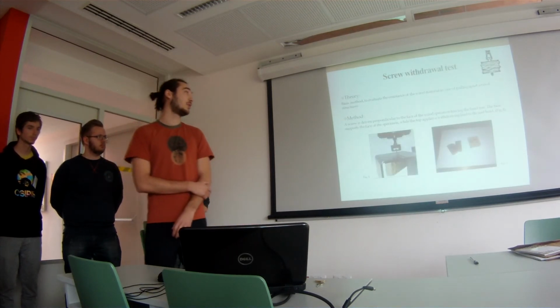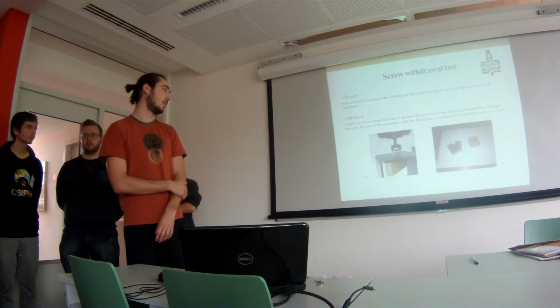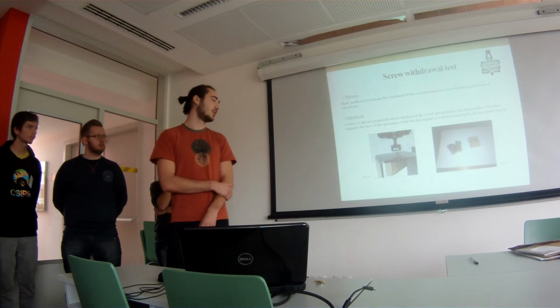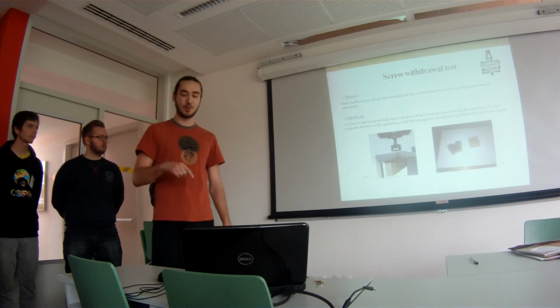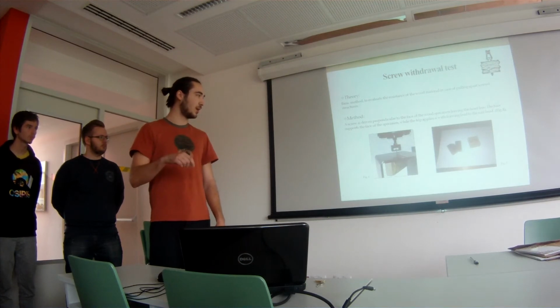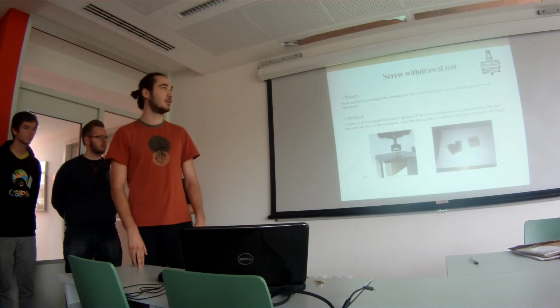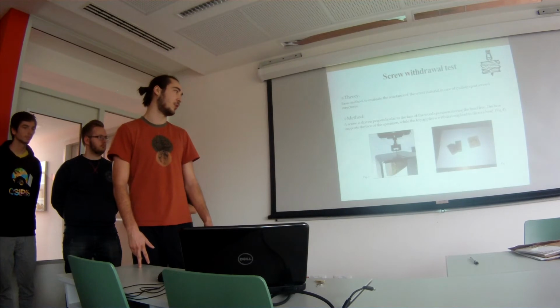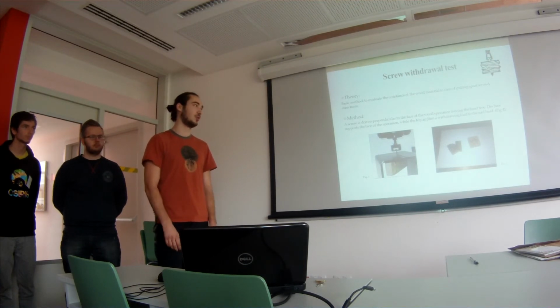The other test was the screw withdrawal test, and basically we put a sample into the machine where there was a screw in the sample, and the machine tried to pull it out, and we measured the force that was needed to take it out. But as we will see, it wasn't good with treated ones.